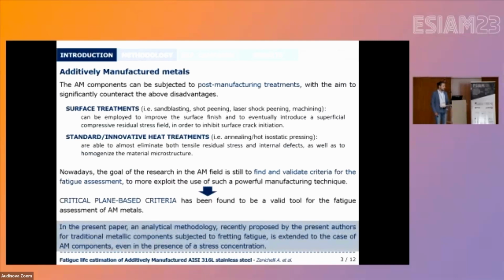In order to counteract the above disadvantages, the AM components can be subjected to some post-manufacturing treatments, that is, surface treatments or heat treatments. And this is mainly in order to improve the surface finish and to introduce a superficial compressive residual stress, as well as to homogenize the material microstructure and to reduce the internal defects.